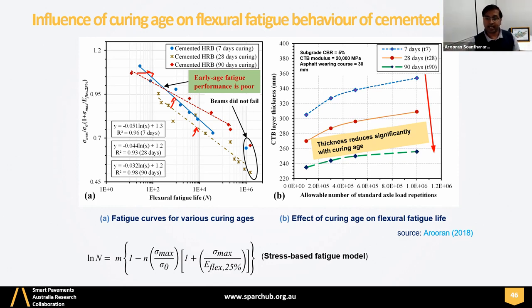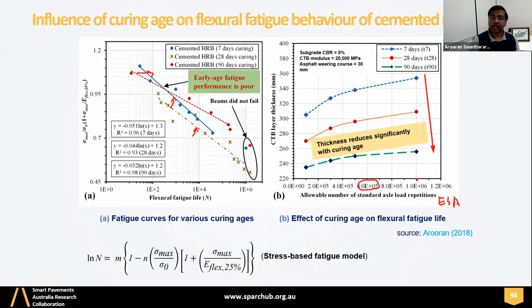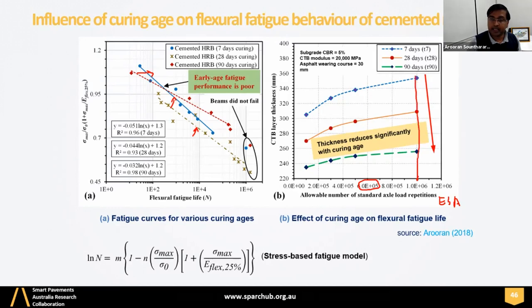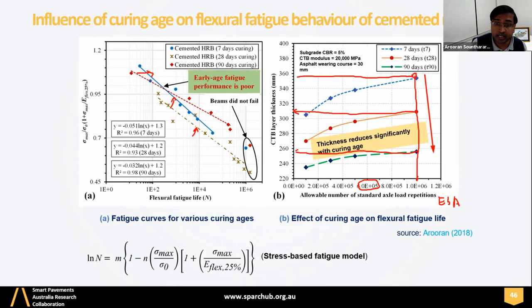So what you see on the right-hand side is the cement layer thickness. This is a typical design using the laboratory data for different curing ages. So your cement layer thickness and the number of standard axles, or in other words, ESAs in the pavement design, is captured in the x-axis. So 1 million means 1 into 10 to the power 6 repetitions. So if somebody wants to design a pavement for 1 million, and what type of pavement? Cement treated pavement. What would be the thickness they need? If they want to open the pavement just 7 days after construction, they need this much, 360. And if they want to wait 28 days, how much thickness do they need? This much. And if they want to wait even further for 90 days, they would need this much.